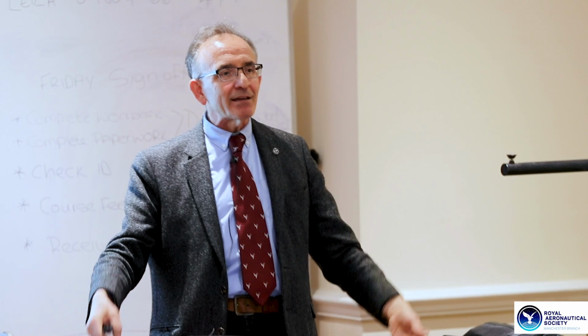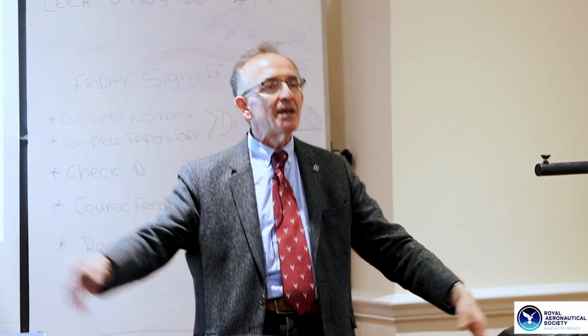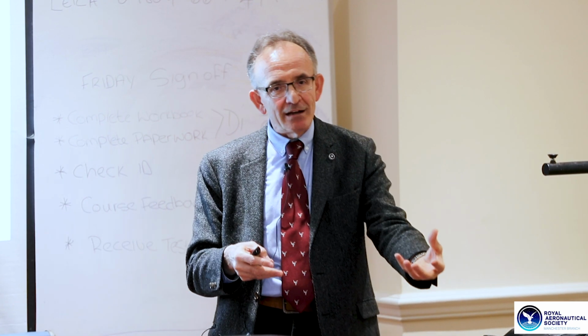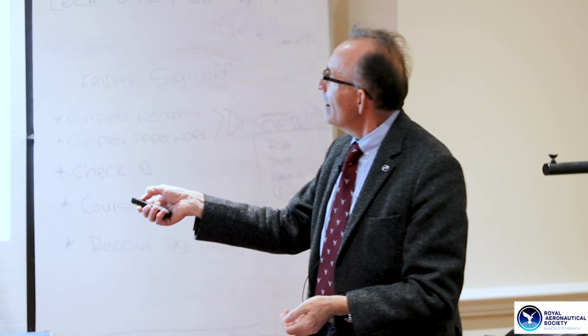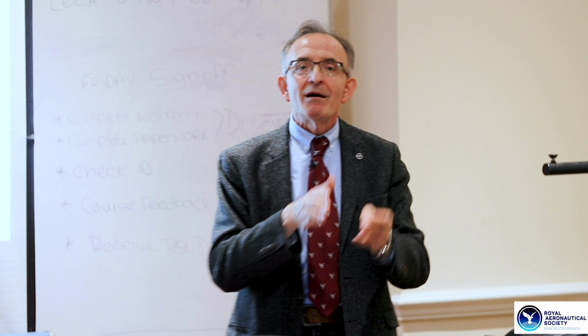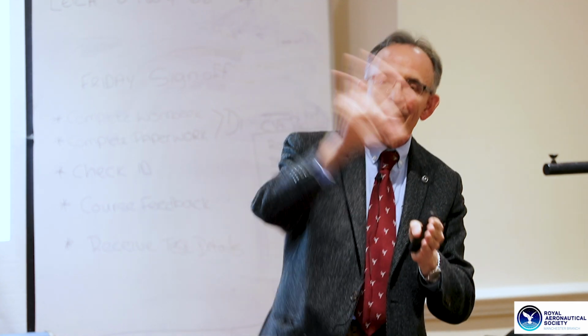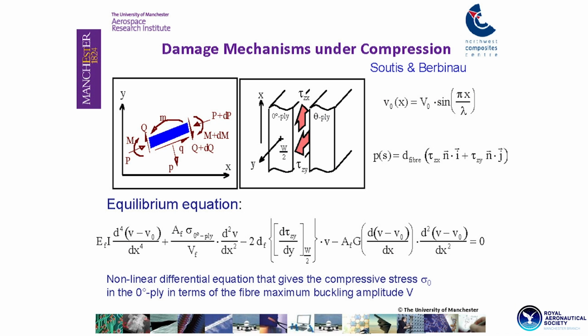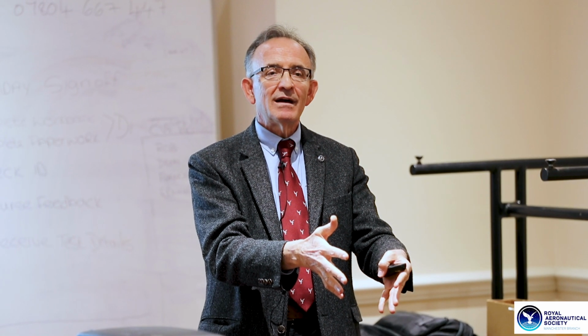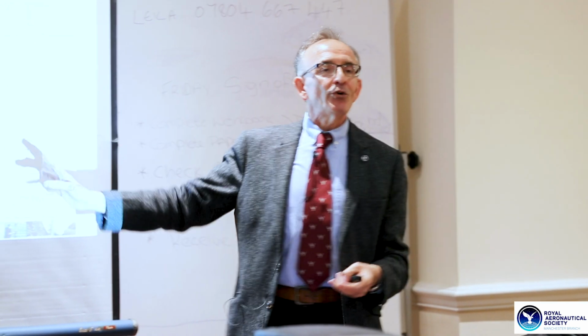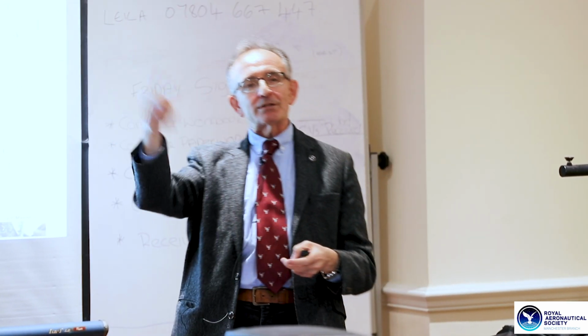If you had a metallic plate, the free edge is stress-free. You have no stresses. In the composite, you have a three-dimensional stress field that this beast here, this component of interlaminar shear, will destabilize further the wavy fibers, and they will trigger microbuckling at a lower applied compressive load. And here, these are the properties, the shear modulus of the polymer that supports the fibers. And it's not a constant value, but it varies with the applied load. So it takes into account the entire nonlinear response of your polymer.